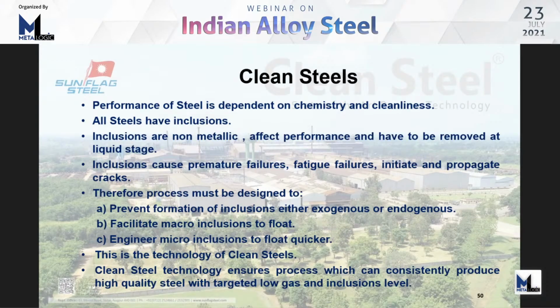The clean steel, the performance of steel is dependent on chemistry and cleanliness. All steels have inclusions. Inclusions are non-metallic, affect performance, and have to be removed at liquid stage. Inclusions cause premature failures, fatigue failures, initiate and propagate cracks. Therefore, process must be designed to prevent formation of inclusions, facilitate macro inclusions to float, and engineer micro inclusions to float quicker. This is the technology of clean steels. Clean steel technology ensures process which can consistently produce high quality steel with targeted low gas and inclusion level.